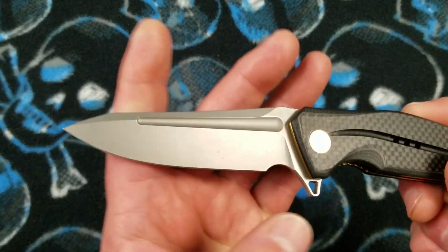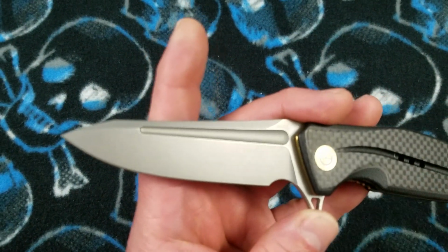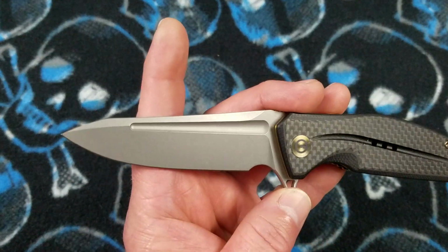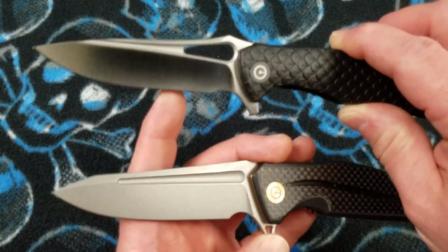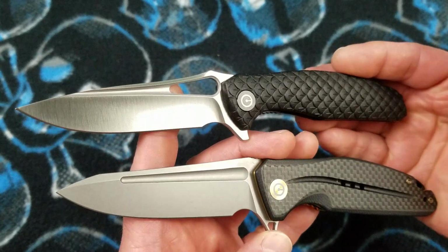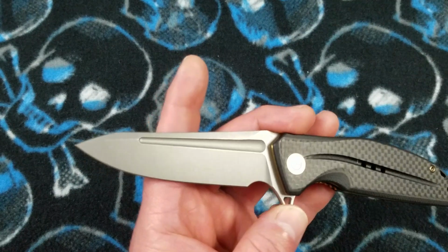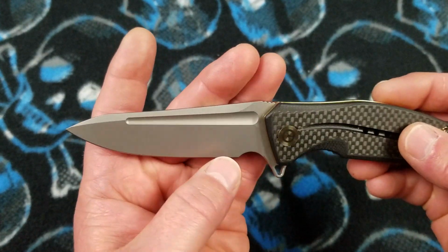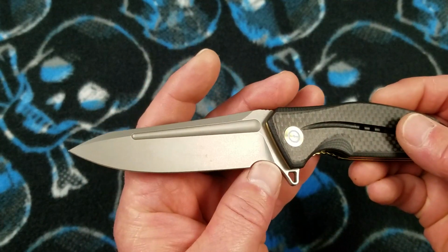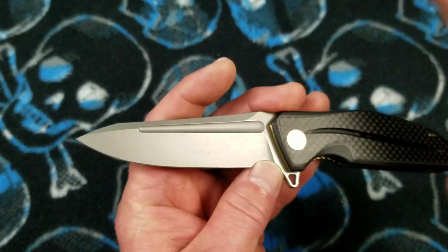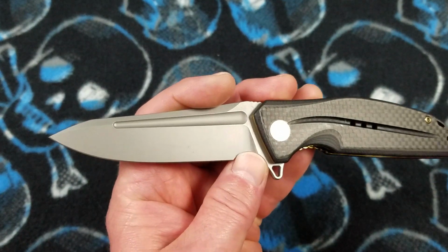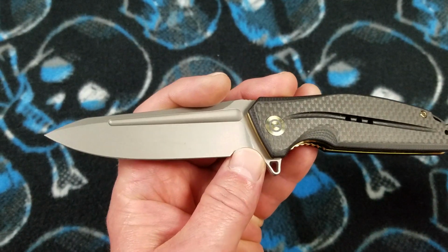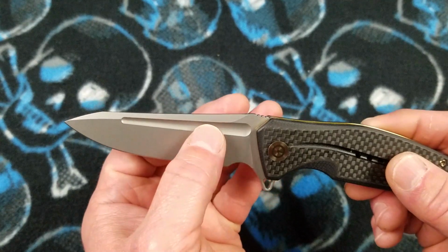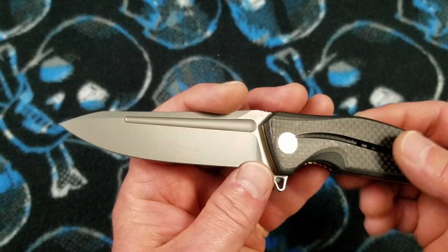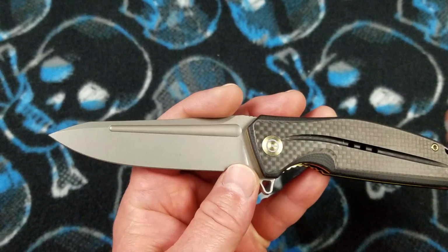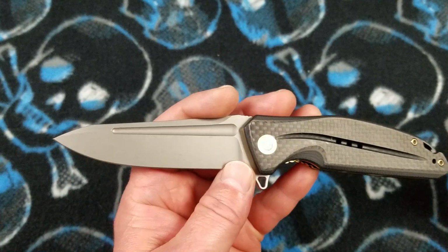Behind the edge thickness. Guys, I recently reviewed another Civivi knife, the Wyvern model, and I talked about how incredibly thin behind the edge it was ground, and this knife is pretty much the same. I hit it in 3 spots along the edge grind, and guys, it was like 18 thousandths of an inch. It's a very thin behind the edge. It's got this nice high flat saber grind on it, but it's very thin behind the edge. 18 thousandths, that's about 0.47 millimeters.